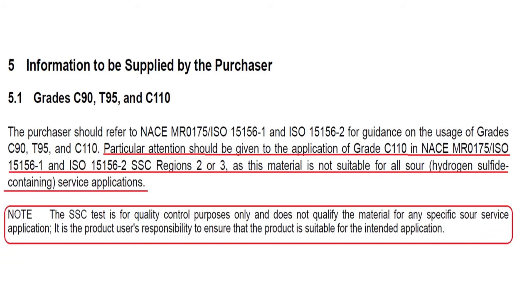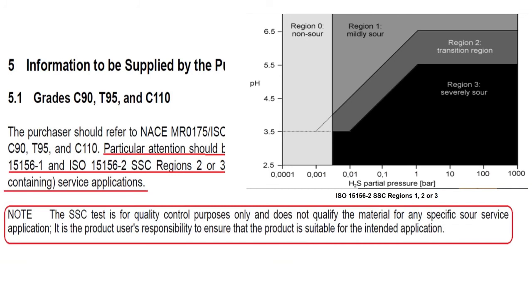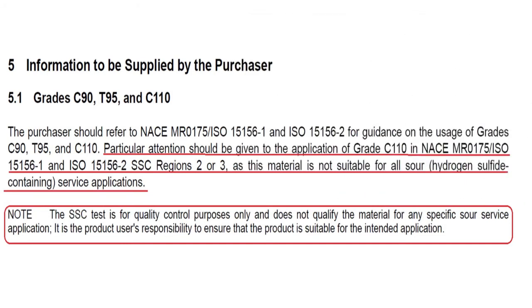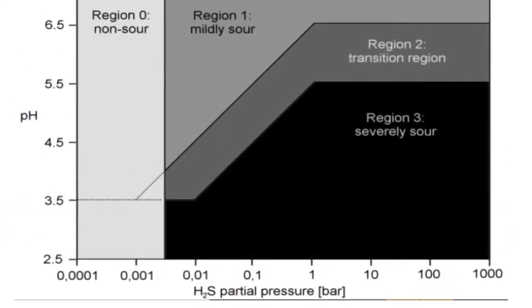So, particular attention should be given to the application of grade C110 in NACE MR0175, ISO 15156-1-2, SSC regions 2 or 3, as this material is not suitable for all sour, hydrogen sulfide containing service conditions. Note, the SSC test is for quality control purposes only and does not qualify the material for any specific sour service application. It is the product user's responsibility to ensure that the product is suitable for the intended application. And we can see in this graph quoted from the ISO 15156-2 standard the SSC regions 2 and 3 that were mentioned in the previous quoted clause from the API 5CT standard.